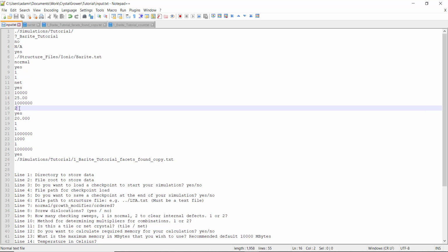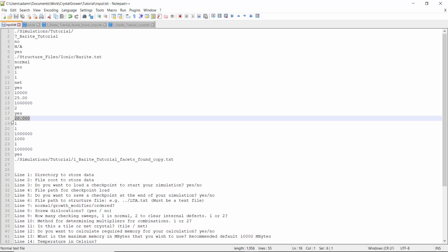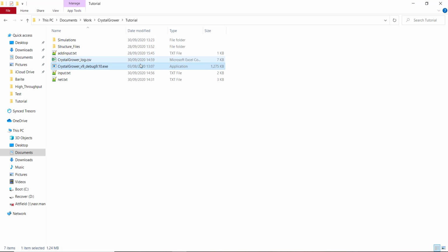So if you pick delta mu mode 2, then it's easy to work out how your excess is behaving across the simulation. I'm also going to change my starting delta mu to 0, because then all of my excess values are going to be based off the equilibrium point of the system, which is also equal to the energy of your kink sites in your crystal structure. So now let's run our simulation and look at the different prompts that show up.